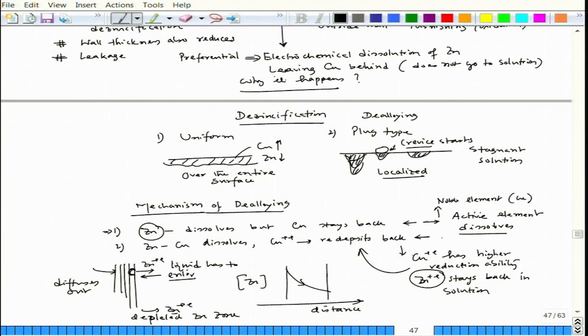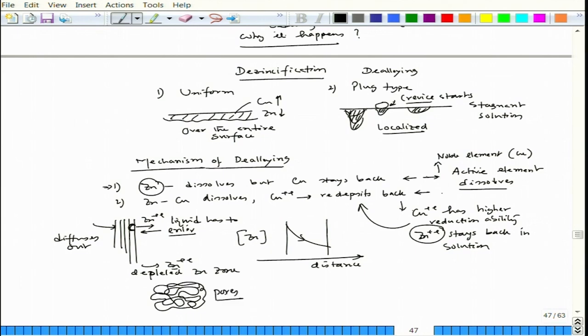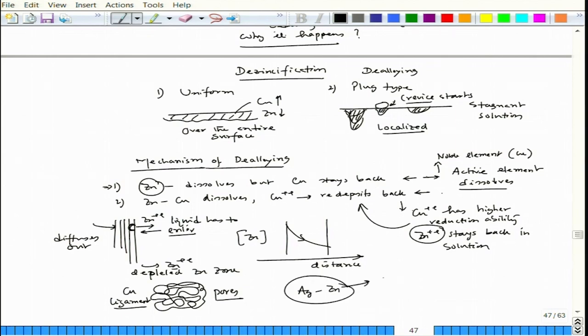Microscopically, when de-zincification happens there is pore formation. These pores form because of de-zincification, and the remaining ligaments are copper ligaments. A similar situation can happen in a silver-zinc system — there also zinc goes out, and silver pores and silver ligaments form.